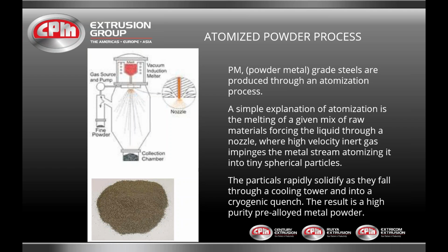The particles rapidly solidify as they fall through a cooling tower and into a cryogenic quench. The result is high purity, pre-alloyed metal powder.